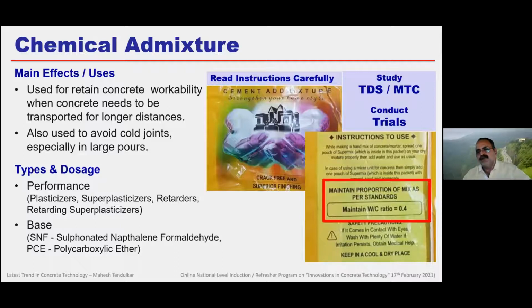So half of the powder was remaining in the packet. When I read it particularly, their instruction said to maintain the proportion of mix as per standard and maintain the water cement ratio at 0.4. Obviously, a 0.4 water cement ratio itself is a good concrete, and maintaining 0.4 water cement ratio is very, very difficult in normal site mixed concrete. So don't always believe it if somebody says I should use it. No, first you experience it, study it. We are engineers, we are the professionals. Study the technical performance, then conduct the trial and only then use it.